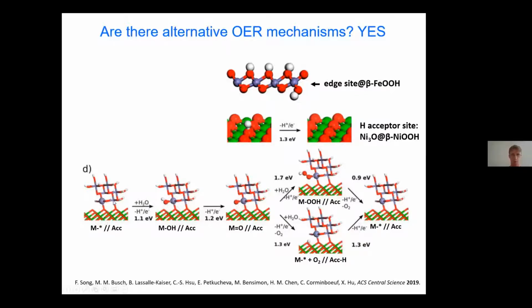So how does it go? We start from empty site, we go to OH, oxo, and then something happens after the nucleophilic attack of water on this oxo group. Rather than going through this metal OOH intermediate or species, the acceptor site is hydrogenated and oxygen is generated in the third step. And this type of alternative road, which is possible when you have two different active sites, causes then the reaction to happen at a lower overpotential.